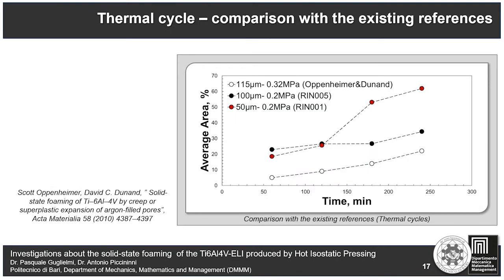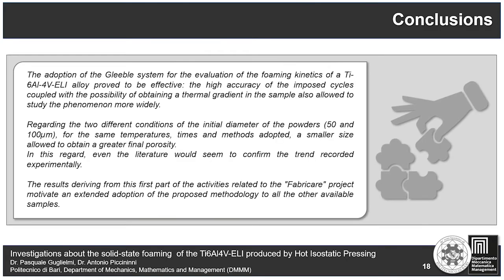Finally, the comparison with the existing references, based on comparable starting conditions and with reference to the thermal cycle condition, shows a greater foaming capability of the material investigated in the present work according to the different investigated conditions. Furthermore, with reference to the initial diameter of the titanium powder, the foaming process seems to be emphasized by low values. To summarize, the use of the Gleeble system to study the foaming process for titanium alloy was useful for the purpose of the research project.